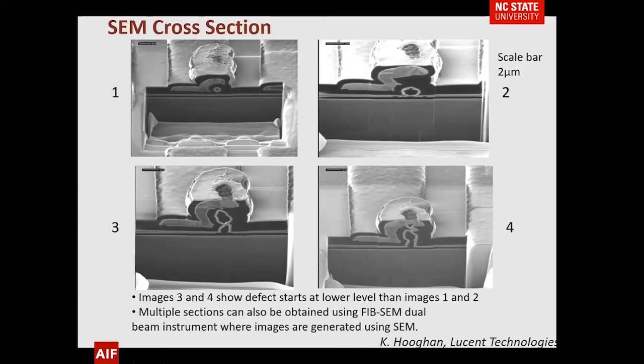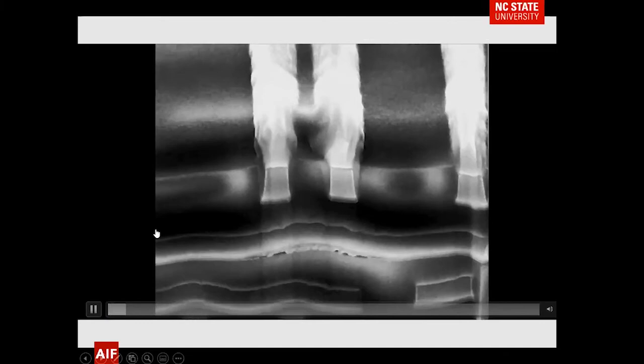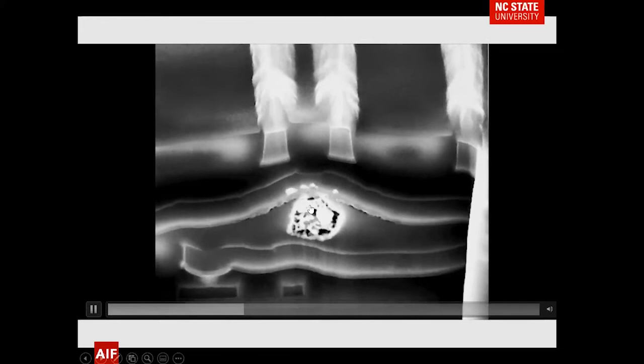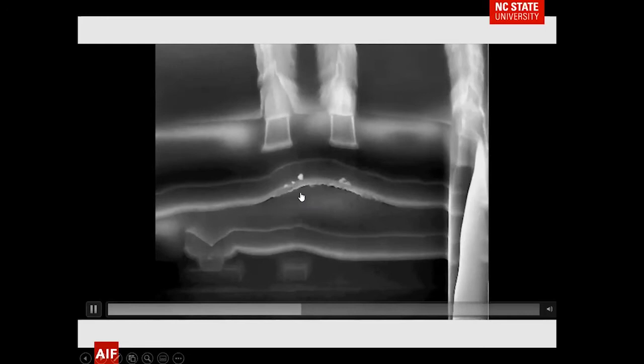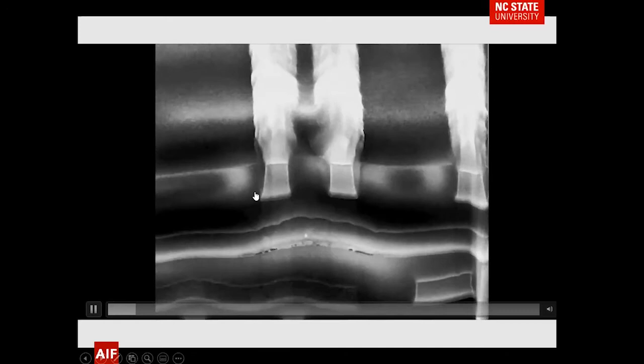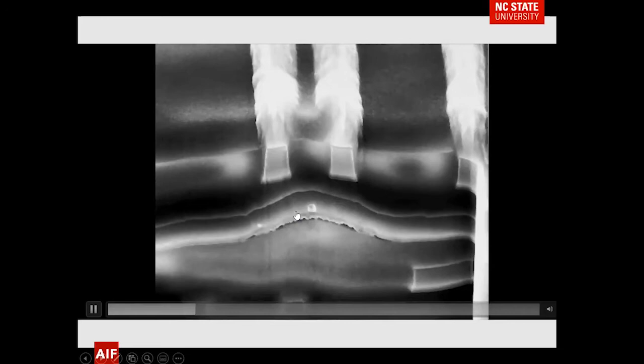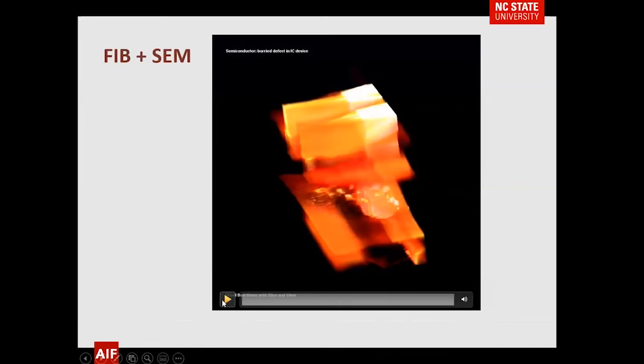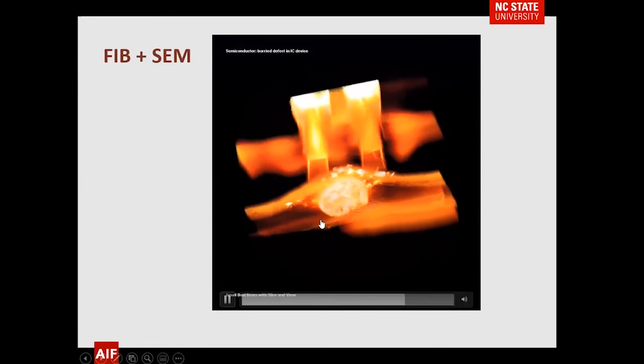I'm going to play a video taken at an instrument vendor site that helped us buy the first dual beam we had in our organization. You'll see we're sputtering through a particular defect — these are aluminum lines. As we sputter through the defect, you see little voids show up within the aluminum lines due to electromigration. We're slicing with FIB and then taking a look. If I put those slices together in a 3D reconstruction, I get a much better idea of the size of the defect and what else is going on.